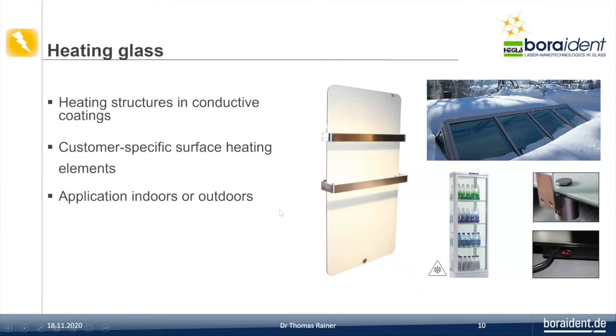The third example I will show you is a special thing if you have a conductive coating on the glass surface itself. If you scribe or remove lines in this coating, then it's possible to make circuits inside such a coating. And then if you put voltage on it, it's possible to heat up this coating, and you have an area heating device. You can use this device in the interior, you see here an example for a bathroom, or outside. If you have overhead glazing, you can reduce the weight of the snow in the wintertime if you melt the snow by heating up this window. And another example is a refrigerator. There is a fog-up effect. You can avoid this fog-up effect if you heat up the glass pane.